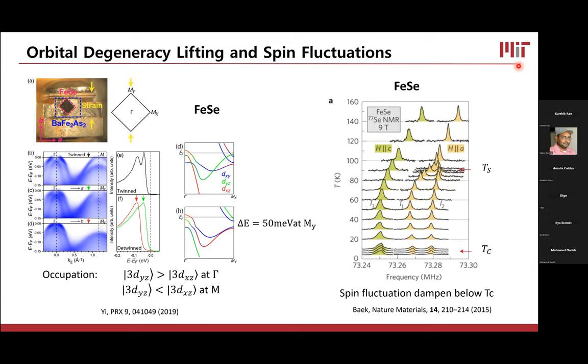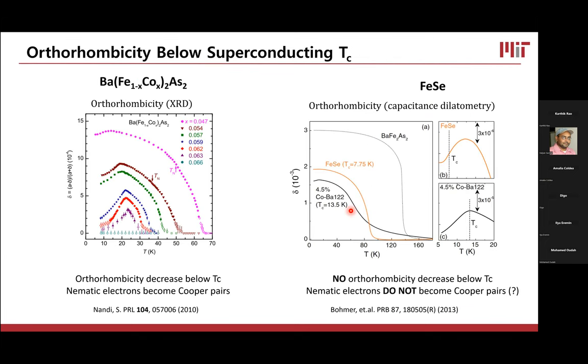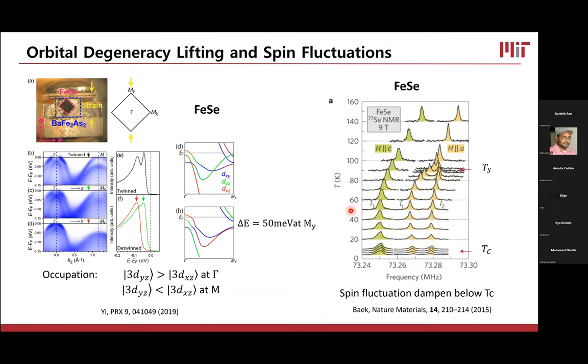Another really interesting piece of data comes from a different NMR study on iron selenide, which showed that once you enter the superconducting phase, the spin fluctuations in the system actually start to damp. So even though up here the orthorhombicity is not damping, the spin fluctuations dampen once you enter the superconducting state. And that's really important because if we want to imagine that all iron-based superconductivity is mediated in some way by spin fluctuations, then it looks like iron selenide has spin fluctuations that are also participating in the superconductivity. So this actually does piece pretty nicely with the idea of orbital-driven superconductivity. Sorry, orbital-driven nematicity.